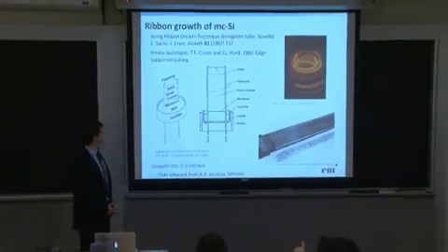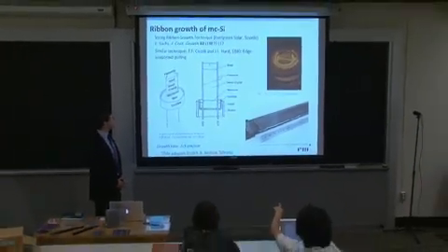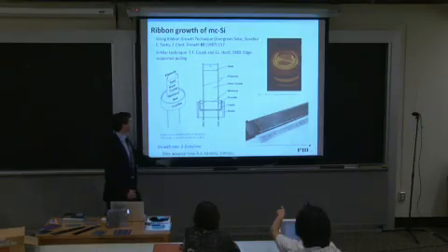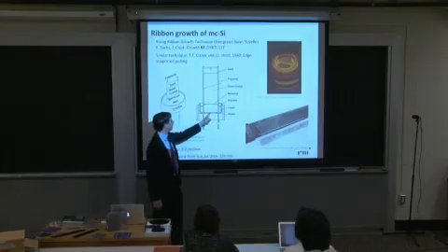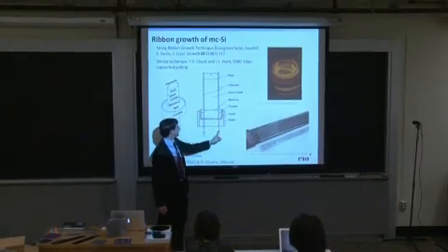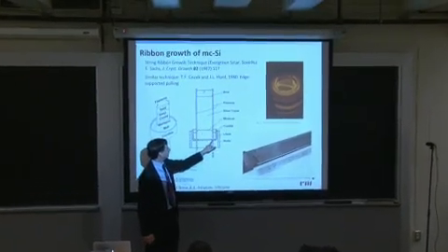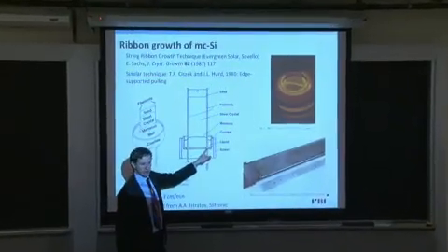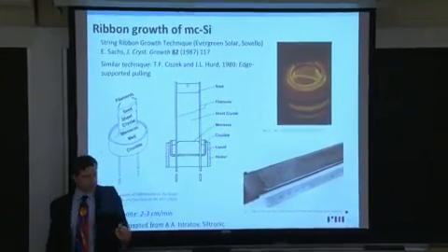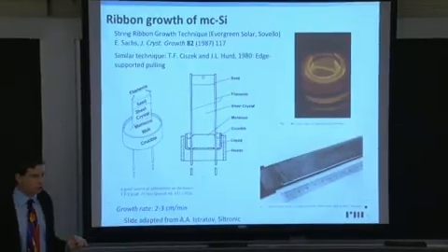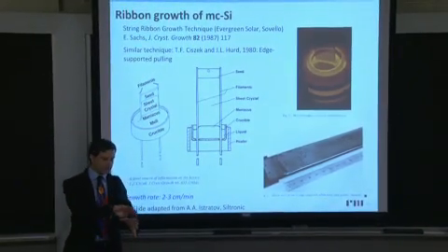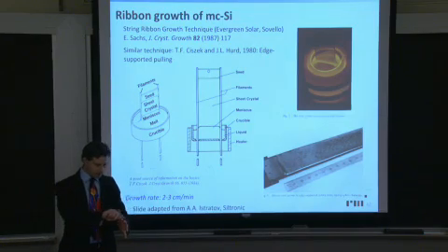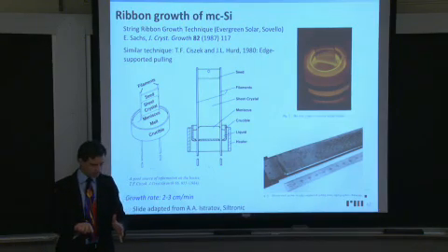Okay. How do you seal the space between the filaments and the bottom of the crucible? Right there, right? Since this is your graphite crucible right here, and these are your filaments popping up through the graphite, the beauty is you don't have to seal that. The surface tension of silicon is greater than that of water. So if you've ever filled up water to the top of a glass and seen that meniscus that forms, the silicon meniscus would be even higher than that.